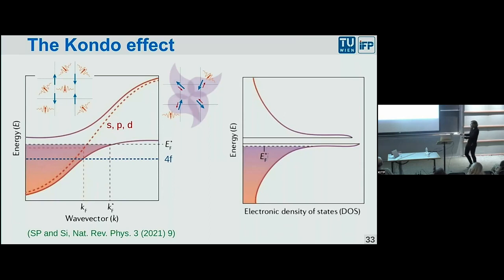Now, it turns out that if you are at low enough temperatures, the interaction between the two subsets will lead to an interaction of these localized states, which by themselves could never interact because they don't see each other, but they see the other electrons from the broad bands. And thus, the whole thing gets what we say correlated or renormalized. In fact, a sort of hybridization occurs between this flat state and the broad band. And we get such hybridized bands.